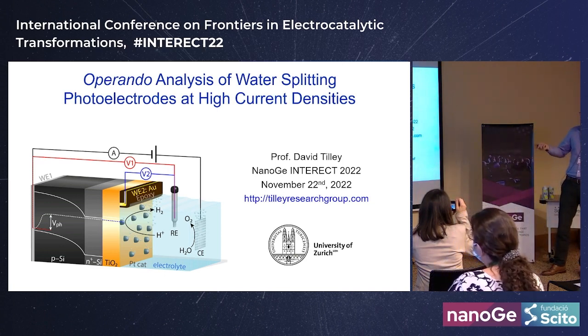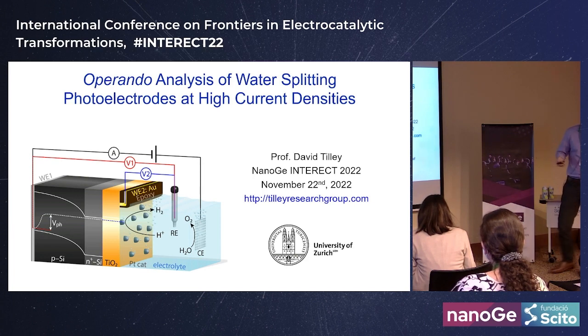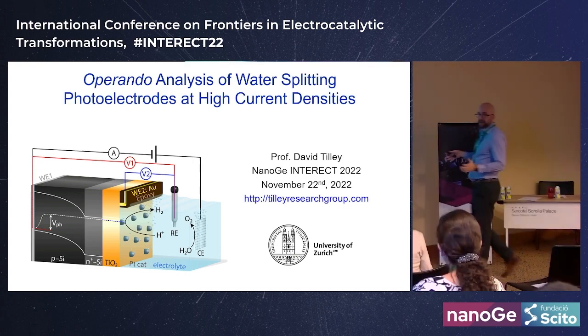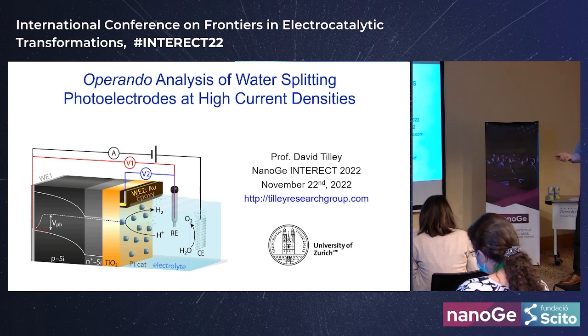You can take advantage of thermal balancing: you're immersing the solar cell material in water or a thin film of water, so you can effectively cool your photo-absorber, keeping photo voltage higher and maintaining higher efficiency under illumination. You're also warming up the electrolyte, which enhances kinetics for your electrocatalytic reaction.